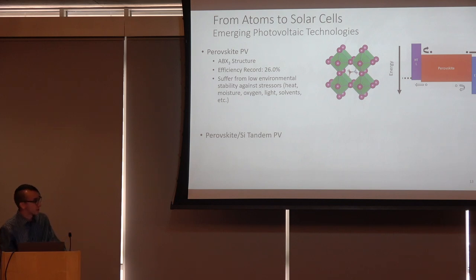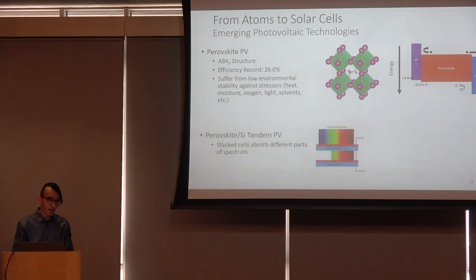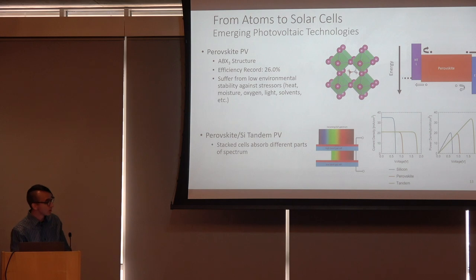Talking about perovskite and silicon tandems, a tandem device is basically a device that just stacks multiple solar cells together, and you pick your solar cells so that they absorb different parts of the spectrum and therefore utilize it more efficiently. If we look at these JV and power curves, in the blue we have a silicon cell, in the orange we have a perovskite device, and then in the green we have a tandem.